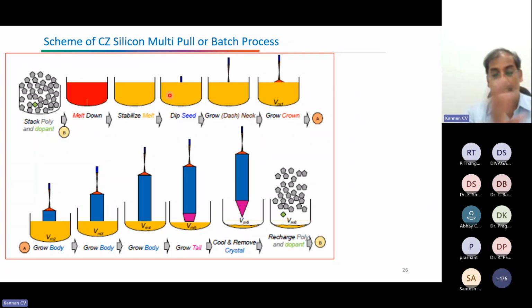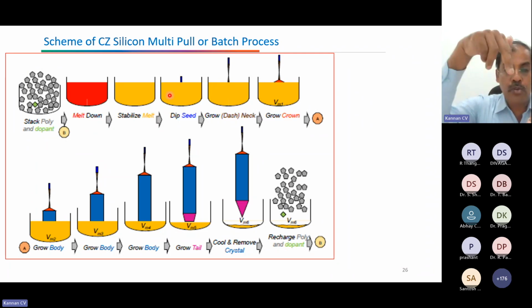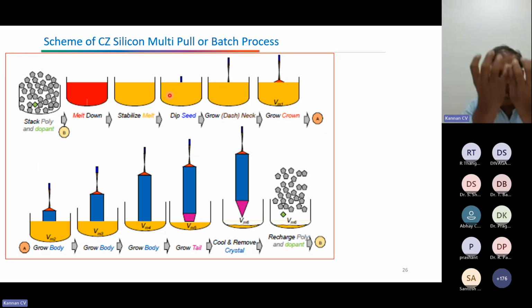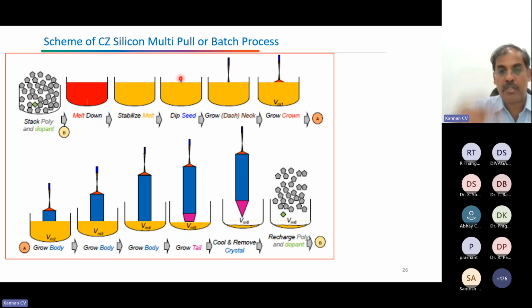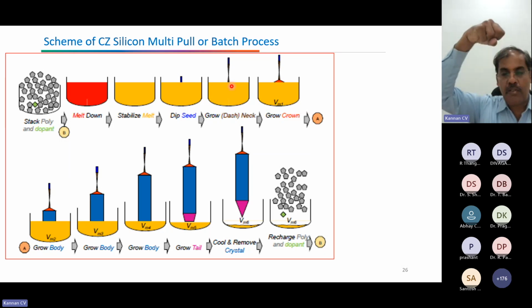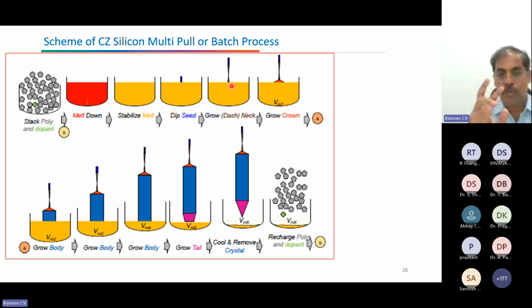In the previous DSS, there was no seed used. After complete melting, you start cooling from the bottom, extracting the heat from the bottom so that the growth will start from bottom to top. Whereas here, after melting, a seed crystal, a small mother seed, will be inserted into the melt. Then the equilibrium will get disturbed, and the melt will start attaching to the seed. Then you have to pull this seed in a controlled way with rotation. At the same time, the crucible also will rotate in the opposite direction.